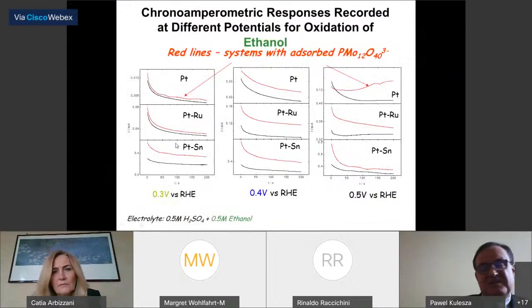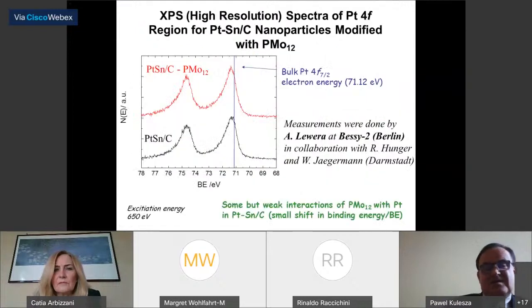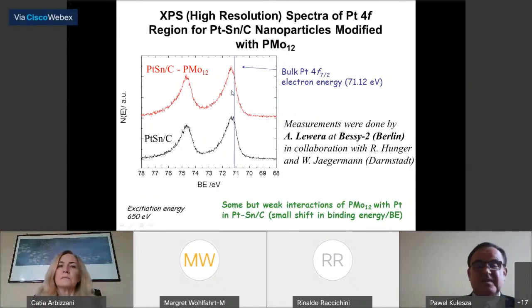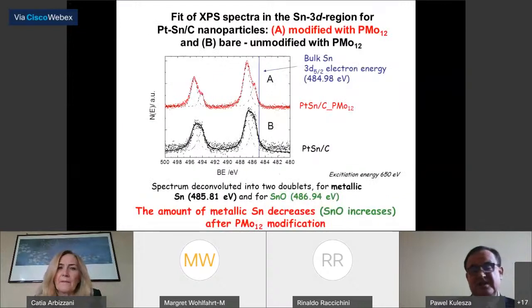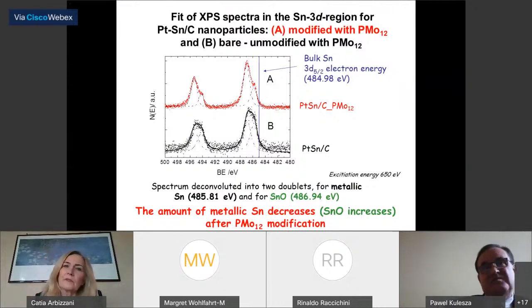In all cases, briefly speaking, with all catalysts, we are getting improvement. Of course, polyoxometallates as a monolayer are not very stable. We know using XPS measurements that, basically speaking, there is not too much change on the platinum side by adding polyoxometallates, but there is a change on the tin part. Tin is a second component which helps with decomposition of carbon monoxide. With ethanol, platinum tin is probably a better catalyst because it is a heterogeneous alloy, and platinum can work separately and tin can work separately.